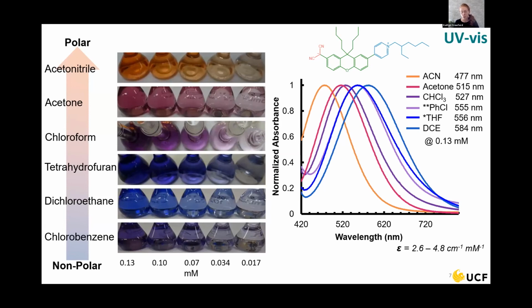One is that because you see the difference in the solvatochromism and it's very strong, that tells us that the chromophore likely does have a very large hyperpolarizability. And so that's a plus, positive. But the other thing is, because there is such a strong shift in the small change of solvents, that also means that it's especially important to identify polymer materials that have higher compatibility with the chromophores in the first place.